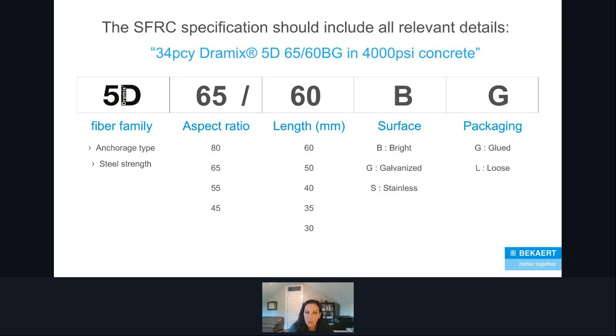The understanding of what all those numbers and letters mean, I'll just break that down for you because that can be a little bit confusing at first. So the 5D is that fiber class or fiber family. Again, as I just mentioned, it's the anchorage and the steel strength. The first number after that is the aspect ratio. The second number is the length in millimeters. And then the first letter is the surface finish, whether it's bright or uncoated, versus G for galvanized. And the packaging, whether it's glued or loose. So we expect anything with an aspect ratio of 65 or higher is going to be glued. Other fibers will be a loose delivery.